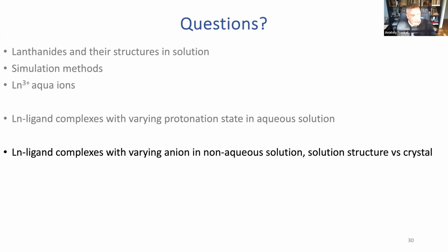So we showed, and probably not just us, but maybe others, that in molten salts, metal ions in a molten state show very strong anharmonicity, precisely because of this fluxional nature of the environment, coexistence of different complexes with different distances, and their RDF is unique and cannot be approximated by cumulants well enough, so that fit results will give very strong underestimation of coordination numbers. So that may even enhance or emphasize the importance of your method, but I think it's important to compare. So I'm just in favor of that.